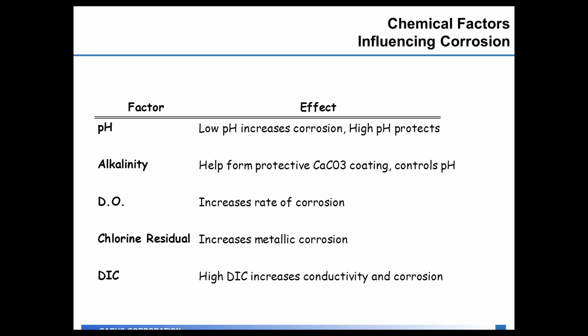How much chlorine residual are you feeding, or are you feeding a chloramine residual versus a chlorine residual? The higher you feed your chlorine residual, that increases the type of metallic corrosion that you have in the distribution system as the chlorine interacts with that scale. Chloramines actually act differently than chlorine, and a lot of research has shown over the years that as you change from chlorine to chloramines to meet other regulations in the drinking water, it can impact your lead and copper numbers in the distribution system.